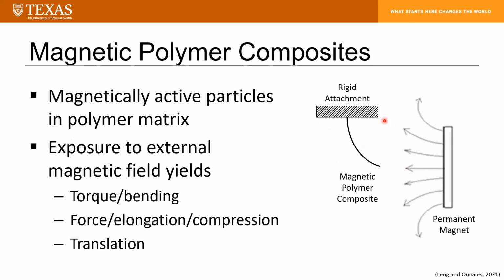Magnetic polymer composites, as you may have guessed, are polymer matrices with embedded magnetically active particles. And so you can get a variety of deformation modes from such composites, depending on the orientation of the composite and the orientation of your external magnetic field. So you can get torque, bending, force that will lead to either elongation or compression. And as is the case with any magnetically active material, if it's not rigidly fixed to something and you can manage to overcome friction and/or gravity, you can also get translation when exposed to an external magnetic field.